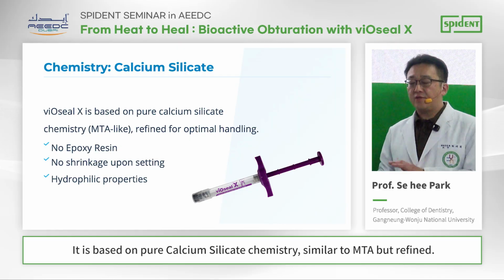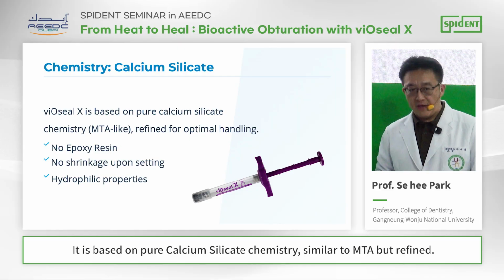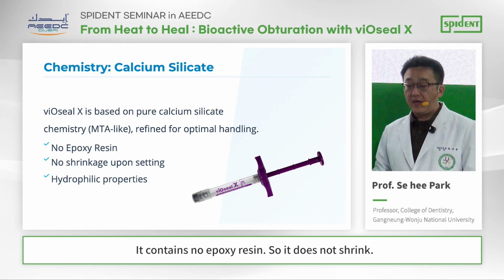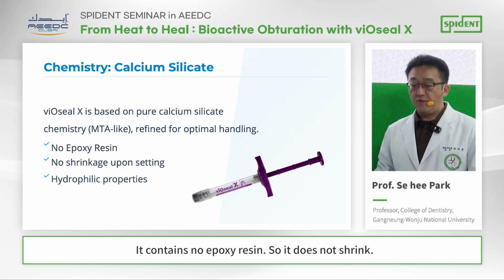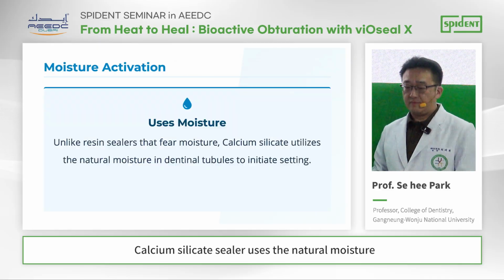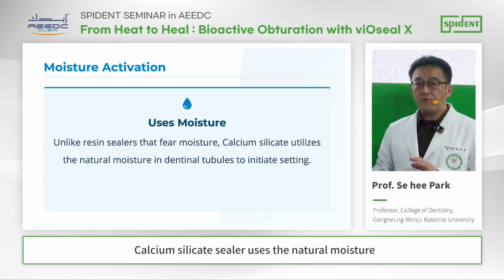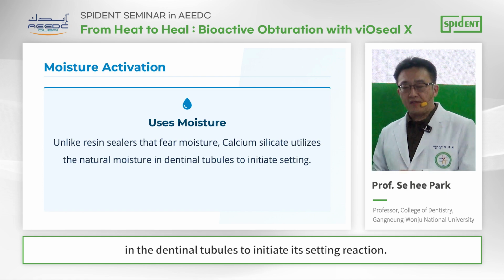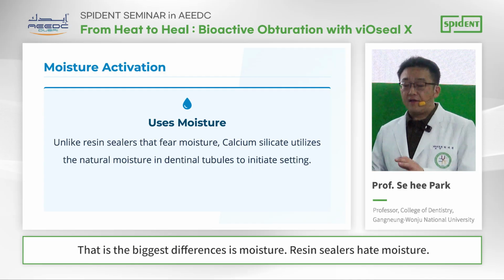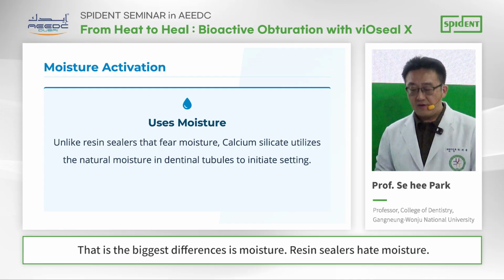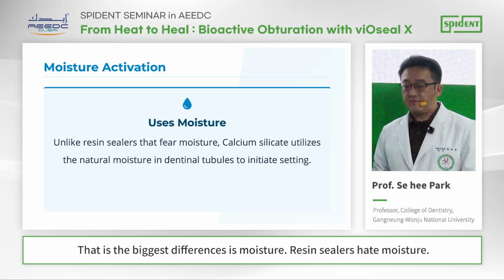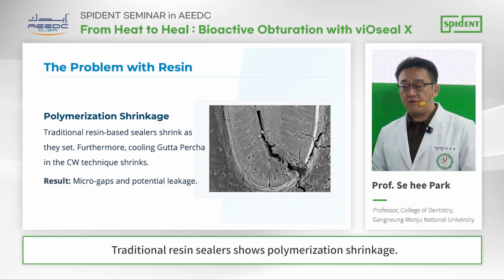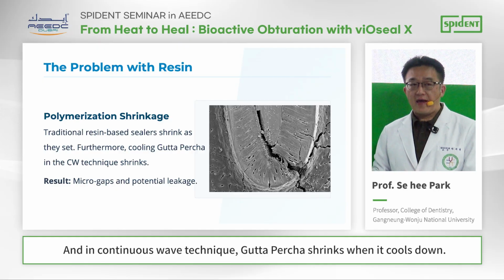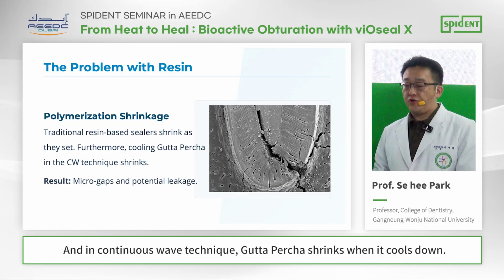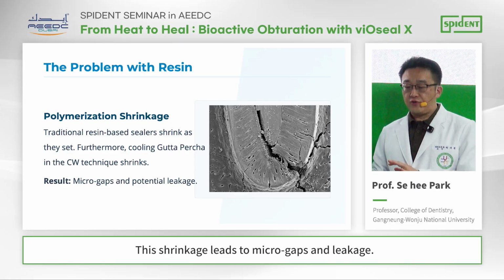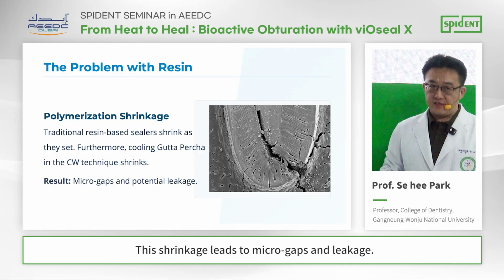It is based on pure calcium silicate chemistry, similar to MTA but refined. It contains no epoxy resin, so it doesn't shrink. Calcium silicate sealer uses the natural moisture in the dentinal tubules to initiate its setting reaction. That is the biggest difference. Resin sealer hates moisture. Traditional resin sealers show polymerization shrinkage, and in the continuous wave technique, it shrinks when it cools down. This shrinkage leads to micro gaps and leakage.